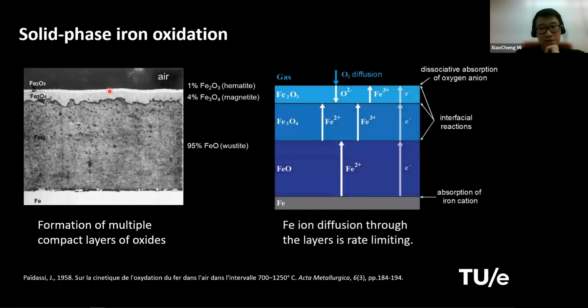And the mechanism driving this oxidation is the following. You have multiple layers, and then in the first layer, you have bidirectional diffusion between iron ions and oxygen ions. And in the other layers, oxygen ions cannot really easily squeeze through because oxygen ions are big, and through this lattice, their mobility is very low. It's mostly depending on the iron ion to diffuse outward and then meet up with the oxygen stored in the lattice to form these layers.